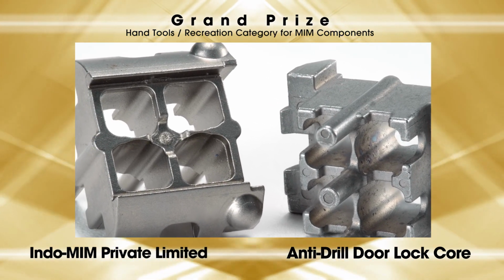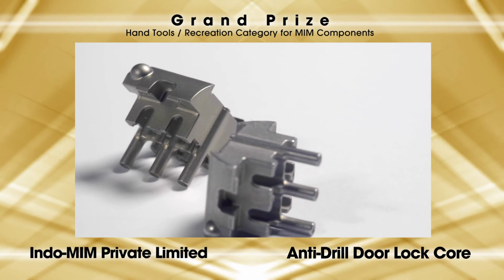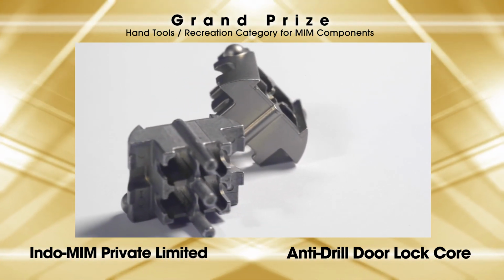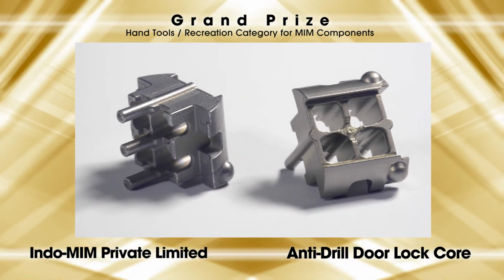The rib-like structures are susceptible to weld lines and short fill due to the thin walls, so a central injection point and hot runners were used for better material flow during molding. Sintering setters were used to retain part shape, and the parts were oriented parallel to the direction of gas flow to avoid distortion at the center of the rib area.